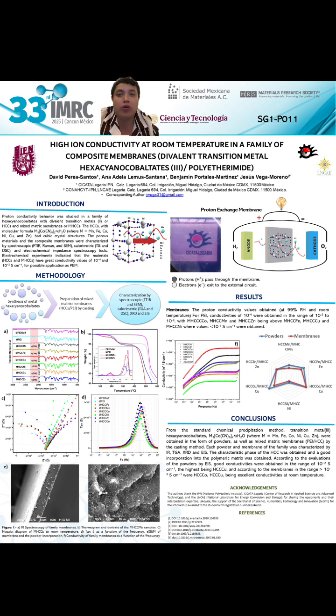To conclude, the conclusions: from the standard chemical precipitation method, transition metal hexacyanocobaltates were obtained in the form of powders as well as mixed matrix membranes by the casting method. Each powder and membrane of the family was characterized by IR, TGA, X-ray diffraction, and electrochemical spectroscopy. The characteristic phase of the hexacyanocobaltates was obtained and a good incorporation into the polymeric matrix was achieved.